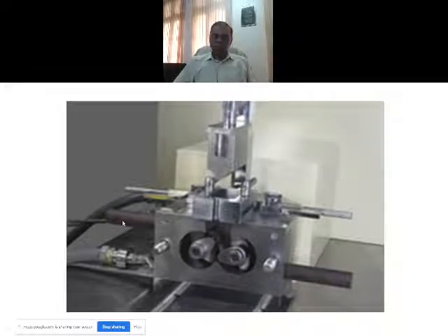Now you see this rod and this rod. That is for removing this plate as well. So this is a rectangular plate with this opening machined very easily, so that it can be taken out as well. And this is an oil heating mechanism. Oil goes in and this will be heated. So the chamber will be heated in this case, because you are not using rubber here. This is mainly for plastic mixing. So when you have plastic mixing, you need to have heating here. This plate can be heated either electrically or using oil. In this case, it is oil heating, oil connection.